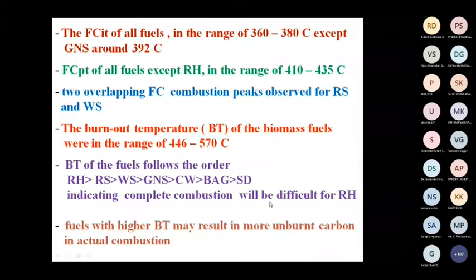Complete combustion will be very difficult. I don't know how many of you observed, whenever rice is given, you end up with a black ash, not white ash. Very difficult. Unless we have very slow combustion, you end up with white ash. Otherwise, rice will result in black colored ash, with high carbon content. So fuels with the higher BT may result in more unburned carbon in actual combustion, especially rice.